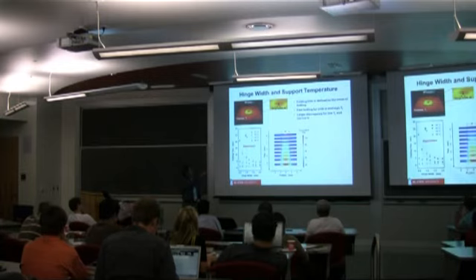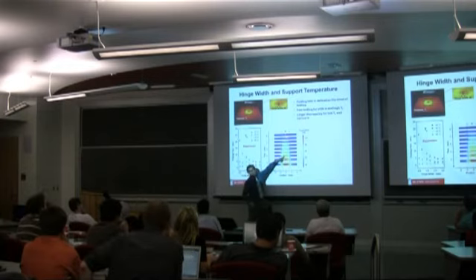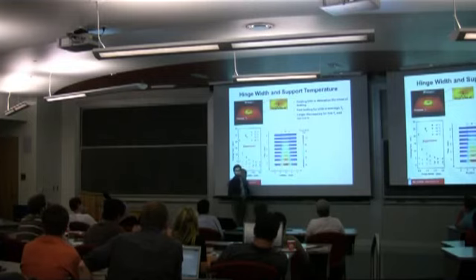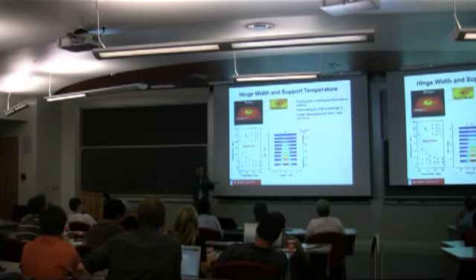And when we shine light on it, you'll see that the top of this surface gets hotter faster than the bottom. So you see this looks a little bit red, this is a little bit yellow. And as a result, you get differential heating. So the top part gets hot, and it allows it to fold.